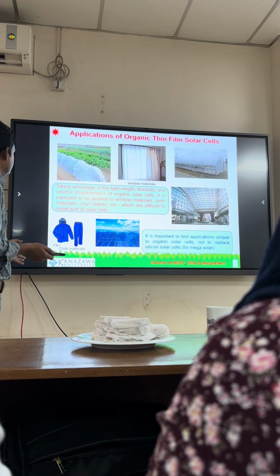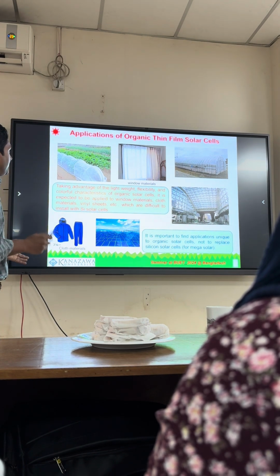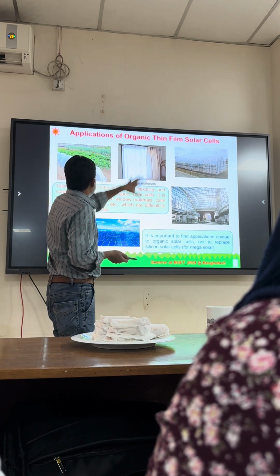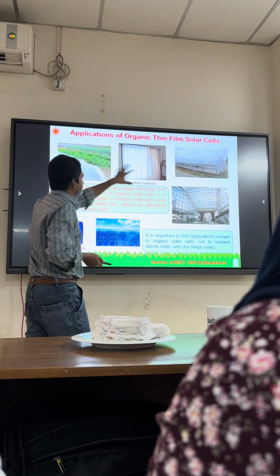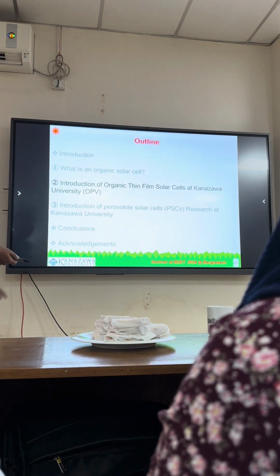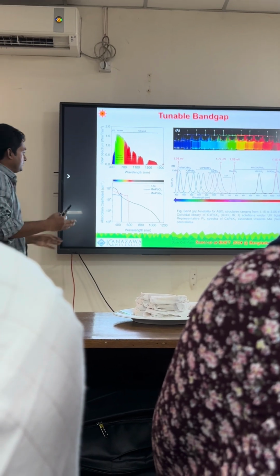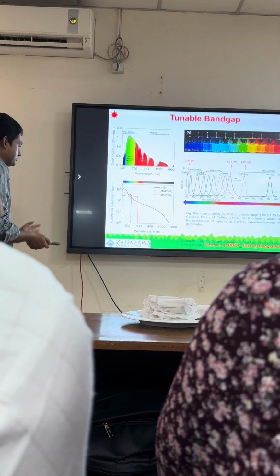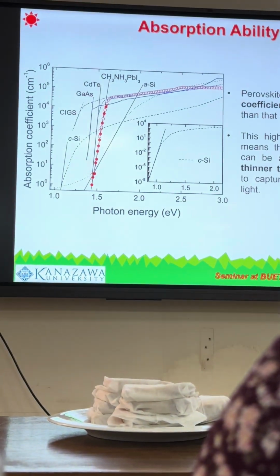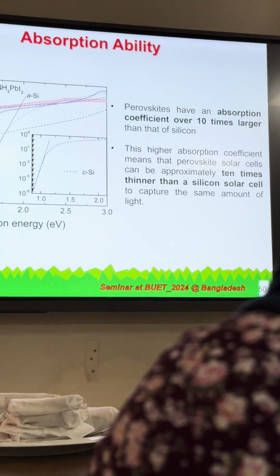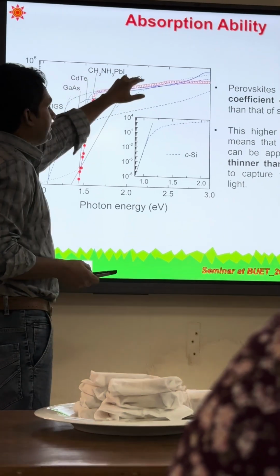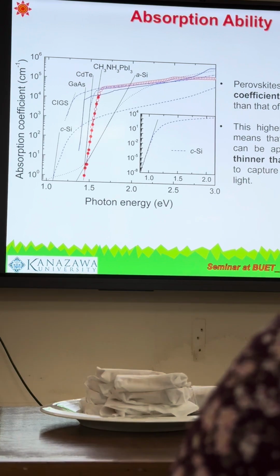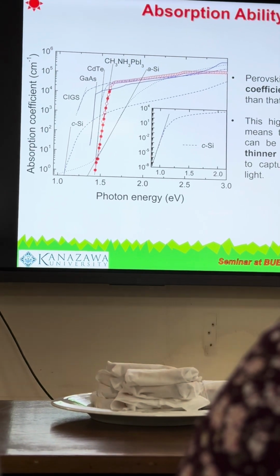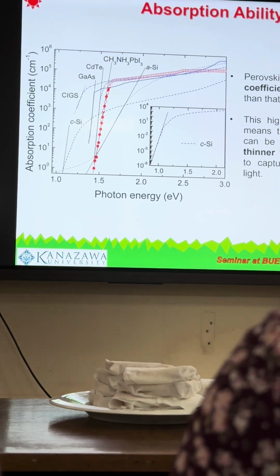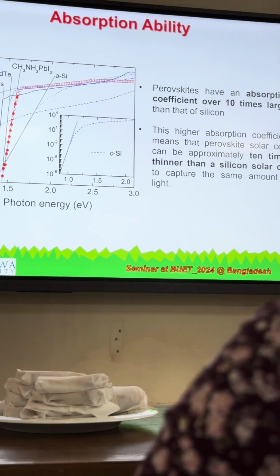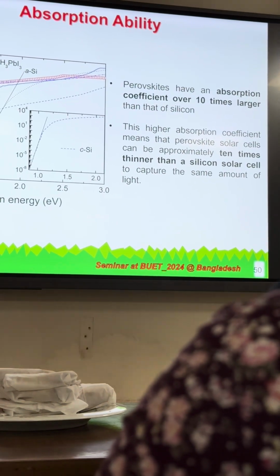And now we are trying to apply our organic type of solar cells in these applications. So for example, the wall, and these are the greenhouse. And then we can go up to 1200 nm wavelength of light that we can absorb. Another important thing is that the perovskite absorption coefficient is over 10 times higher than silicon. So silicon is several micrometers thick, but for perovskite we can consider the thickness to be less than 1 micrometer, which can give sufficient light absorption.